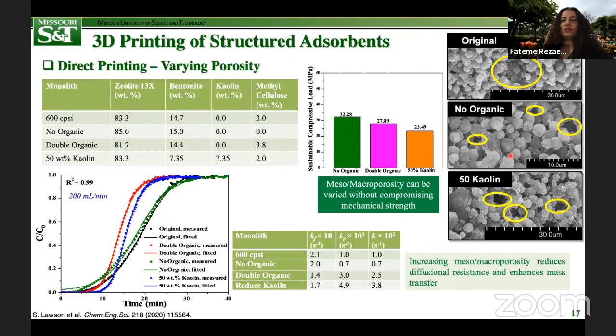Now, how about the porosity effects on dynamic adsorption behavior? Simulating the concentration wavefronts and estimation of mass transfer parameters indicated that increasing mesoporosity reduces diffusional resistance and enhances mass transfer. To put it numerically, the Kp values, the Kf values, and overall K values were estimated, and it was found that Kp, especially pore mass transfer coefficient, could be increased substantially in the meso or macroporous monoliths relative to the original 600 CPSI monolith formulated by a mesoporous binder.